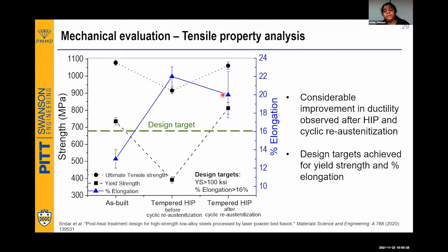So from this design, what we have found is that we now have a steel with very low porosity, that is 0.7% only, but with very good yield strength and very good ductility. Initially, the porosity was high, yield strength was good, but ductility was bad. But now the porosity is low, the yield strength is also high, and the ductility is also high. And this is the success of this design.